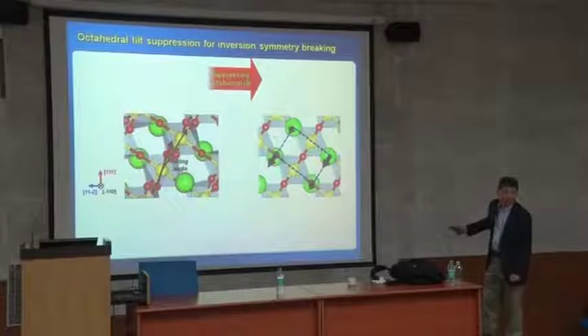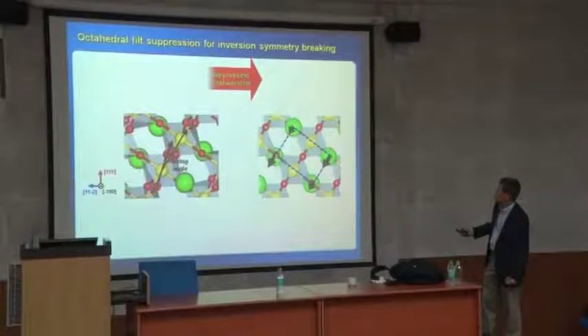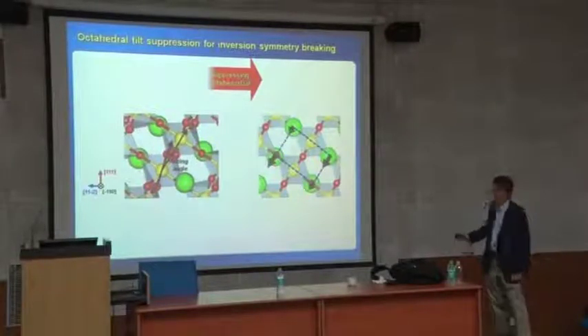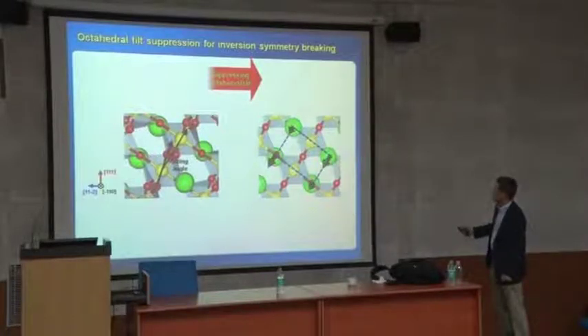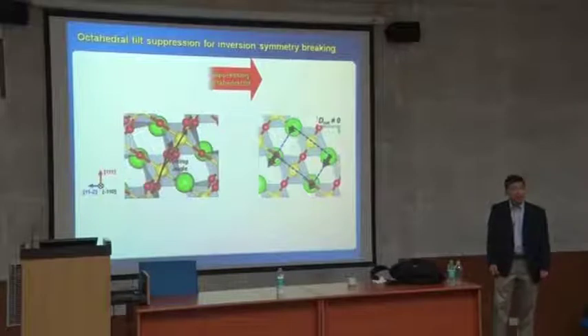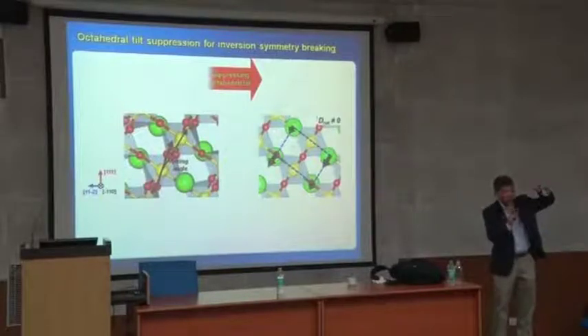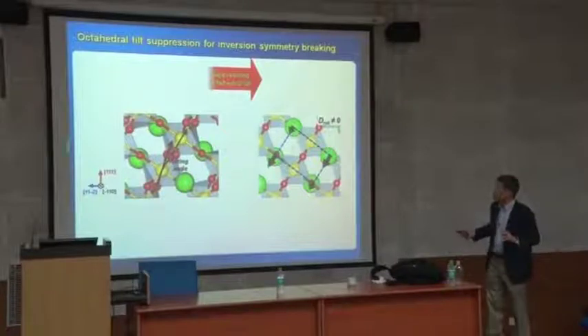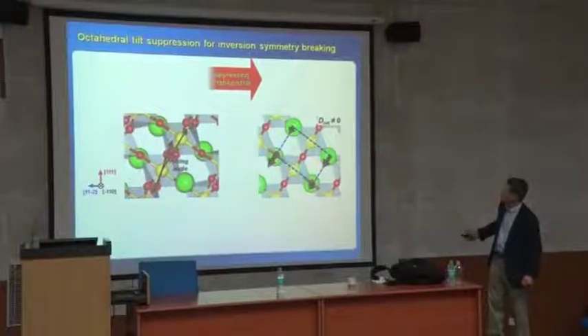You stretch it. When you stretch this, what happens is this one becomes shorter, this one becomes longer. Okay? And this one longer, and this one shorter. So that means that those two, net is non-zero, okay? Because this is longer and this is shorter. And then when you look at this octahedral tilting, because it's hard to draw a three-dimensional drawing here, but in the three-dimensional drawing, you see that this octahedral tilting makes this one stretching, and the tilting angle between here oxygen to this cation is bigger.